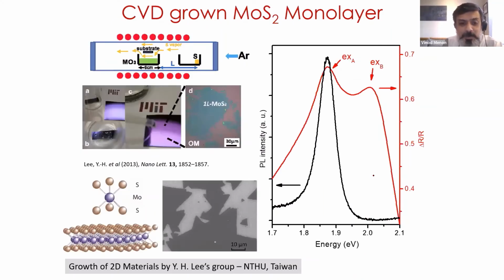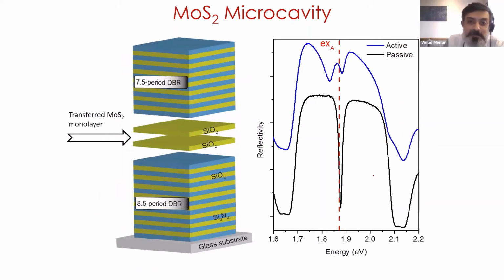So when we started this work back in 2015, we weren't that good with Scotch tape. So we just got CVD grown materials. We took this material and put them between two mirrors. So this is a mirror, this is a mirror, and then we transferred the 2D material in here.